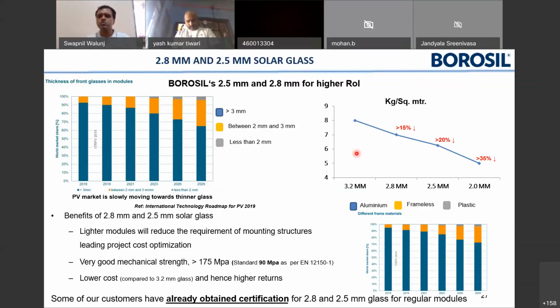So just to give you the background, the 2.8 mm thickness glass is at least 15% lighter as compared to 3.2 mm. 2.5 is 20% lighter, and ultimately 2 mm glass is 35% lighter as compared to the normal glass. So we will ultimately see lighter modules, which will reduce the requirement of mounting structures, which will again help you have a lower project cost.